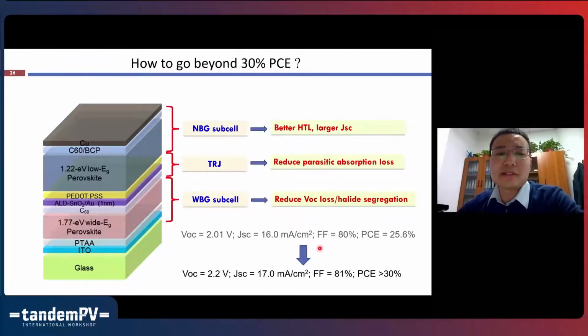Next, I want to stimulate us to think about how to really go beyond 30% efficiency for all-perovskite tandem devices. I think Steve later will also discuss in more detail how to achieve above 30% efficiency in perovskite-based tandem devices. So here I will just show my personal views on how to reach this goal. If we look at our current results, we still have quite a low VOC value. That is mainly because we have quite large VOC losses in the wide bandgap perovskite solar cells. If we can further reduce this VOC loss and also further suppress the halide segregation in the material, we have a good chance to get the VOC value above 2.2 volts. I think that is not a big challenge.